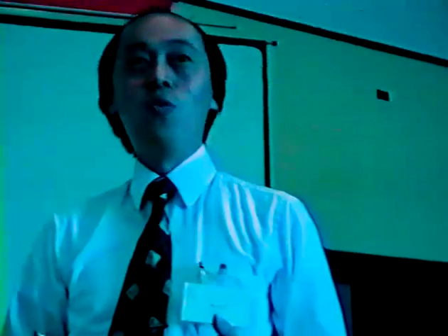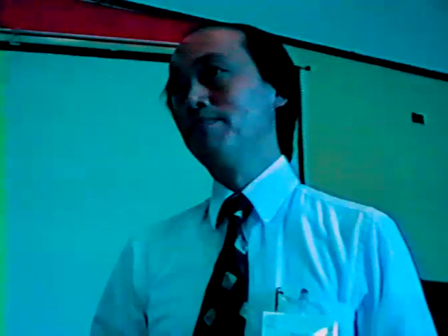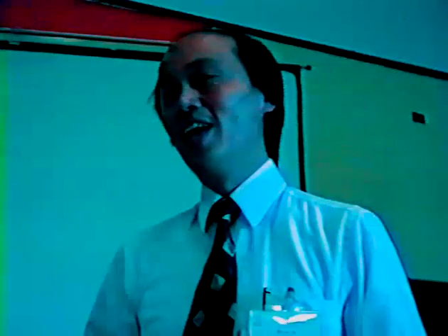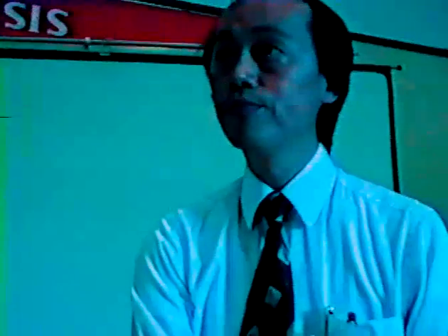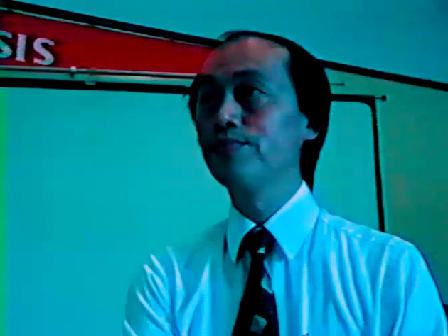Okay, your comment is very well appreciated because not only for zirconia, for other oxides, the loss in surface area upon heat treatment is mostly related to kinetics of sintering and crystallization. And it's well known that impurities will do that. So what we observe could be explained by just having impurity retarding the transformation. In fact, one way to stabilize zirconia is to dope it, as you well know. I cannot prove to you that we absolutely have no impurities, but I think what we have stabilized is in fact a material that is pure, and the stabilization comes from the structural integrity through the supercritical drying.